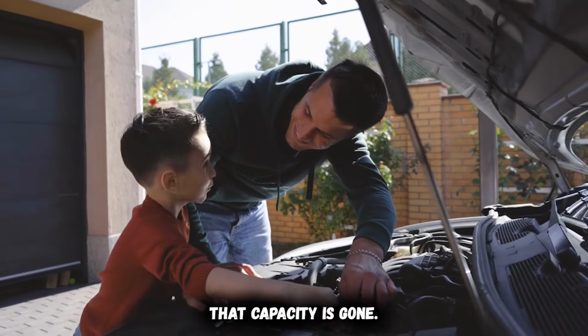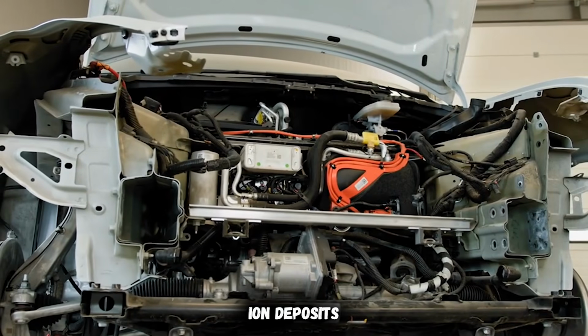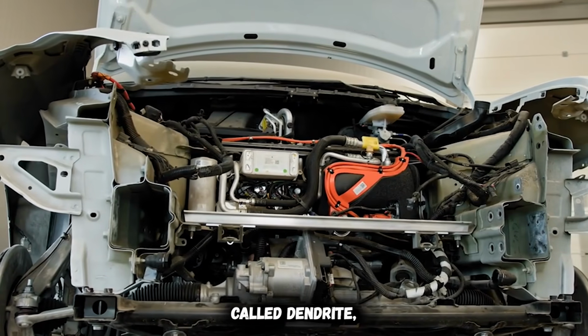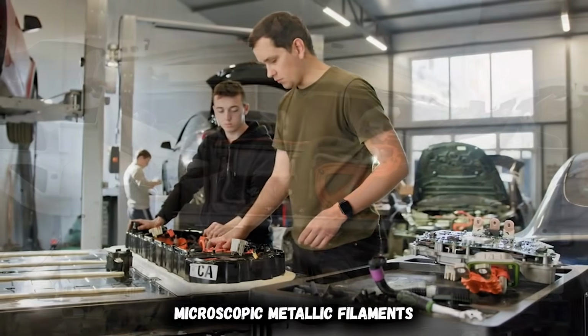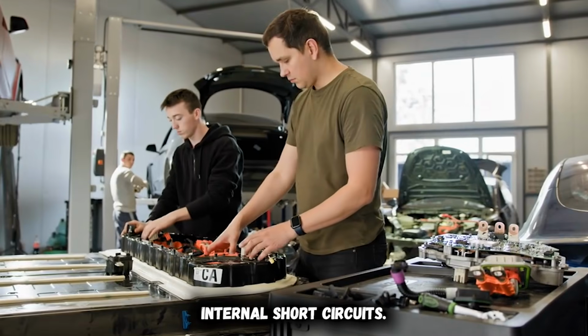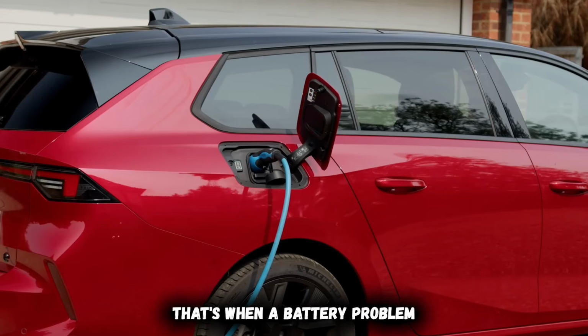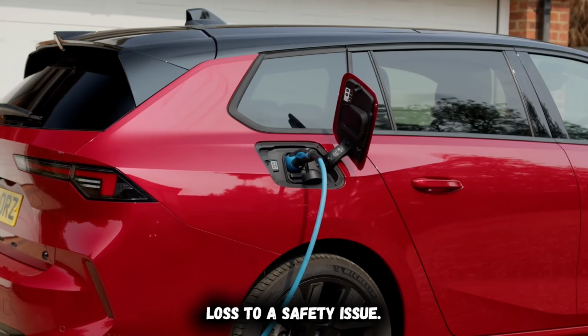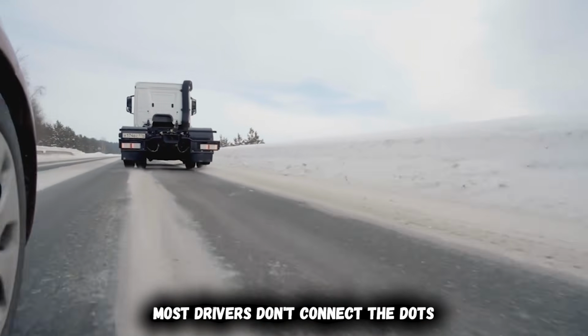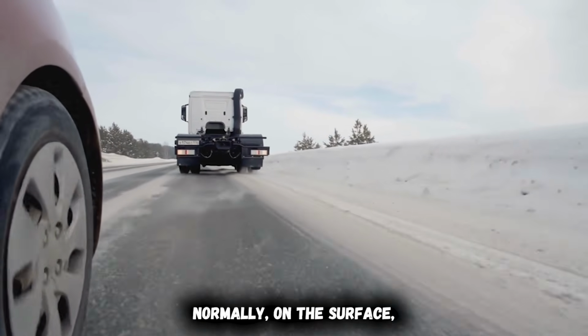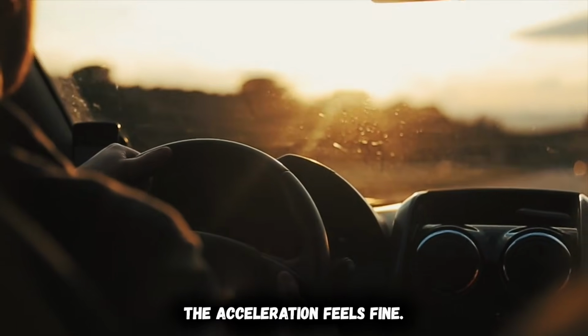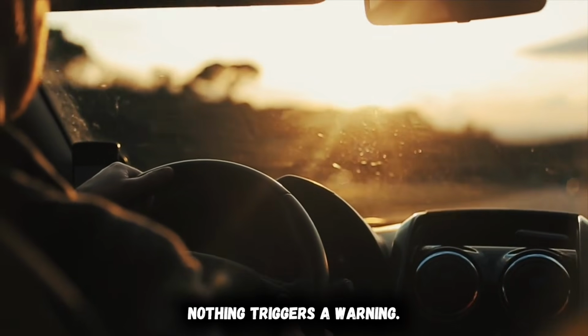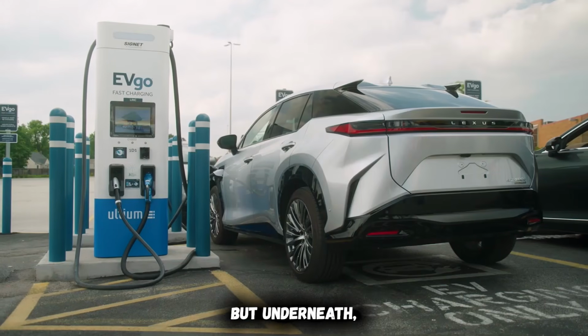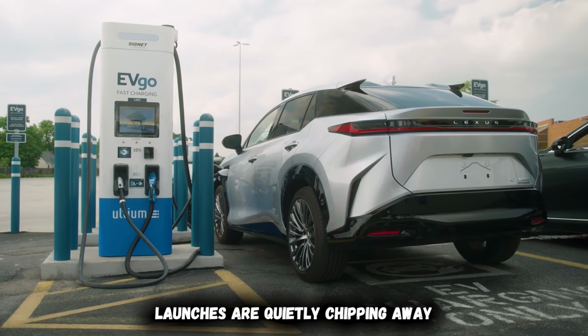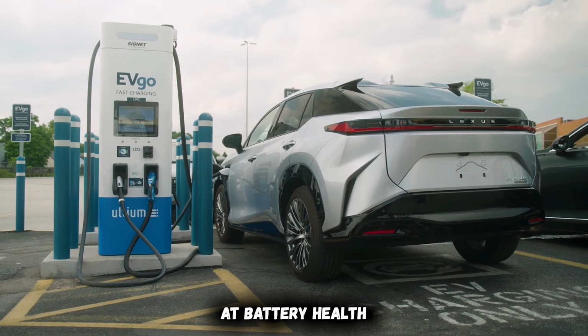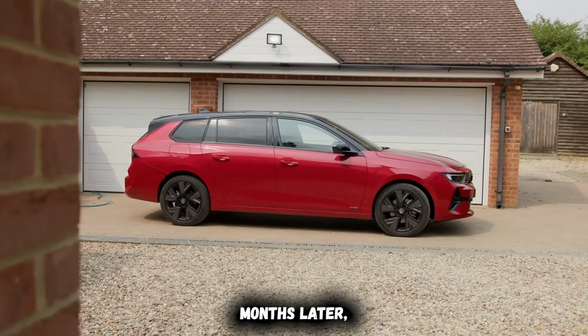That capacity is gone, and over time, those lithium deposits can develop into structures called dendrites, microscopic metallic filaments that can eventually cause internal short circuits. That's when a battery problem goes from gradual capacity loss to a safety issue. Most drivers don't connect the dots because the car responds normally on the surface. The acceleration feels fine, nothing triggers a warning. The car doesn't limp or stall, but underneath, repeated cold, hard launches are quietly chipping away at battery health in ways that only show up in the data months later.